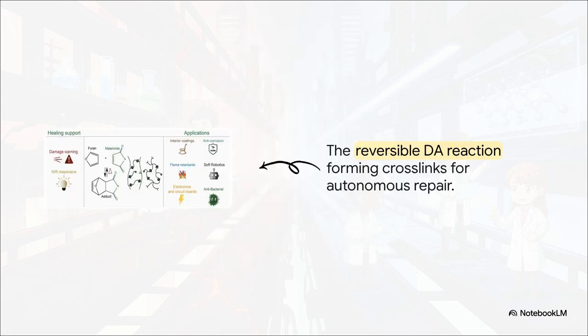And it builds into something even more astonishing: stimuli-responsive chemistry. Some of these smart polymers don't even need to be physically broken to release their payload. They actually respond to changes in the environment itself, like a spike in temperature or a drop in pH caused by corrosive ions. A great example of this is the Diels-Alder reaction. It allows the polymer to form reversible crosslinks. If the material is damaged, an environmental trigger causes the molecular bonds to autonomously relink and heal, completely sealing the barrier back up without anyone lifting a finger.